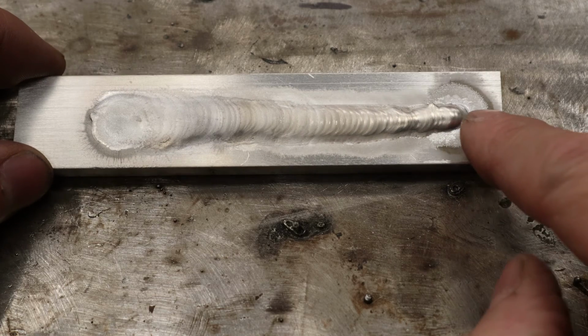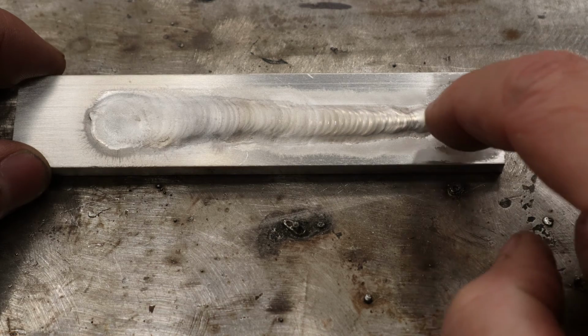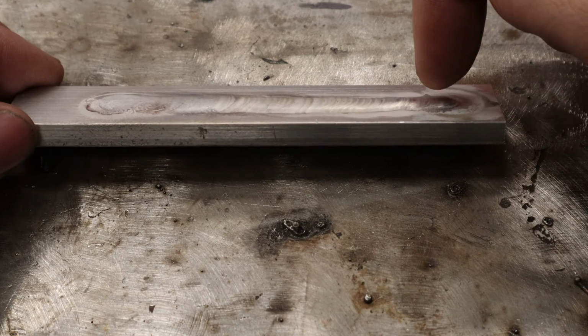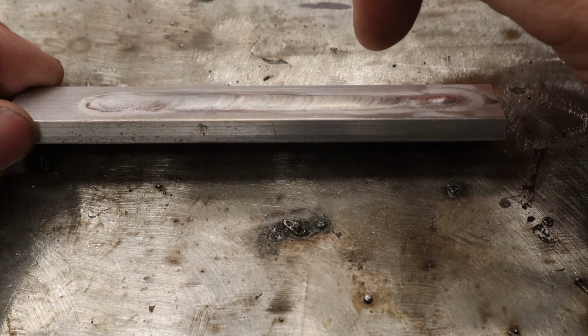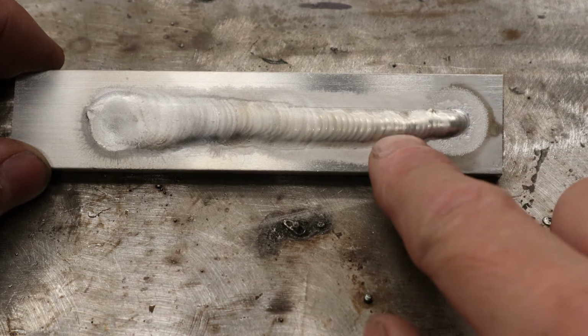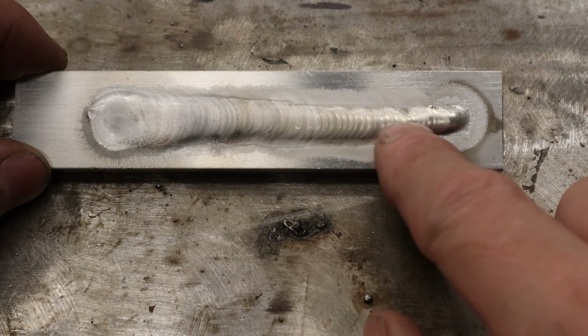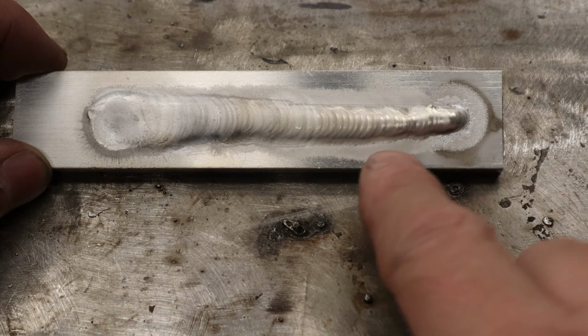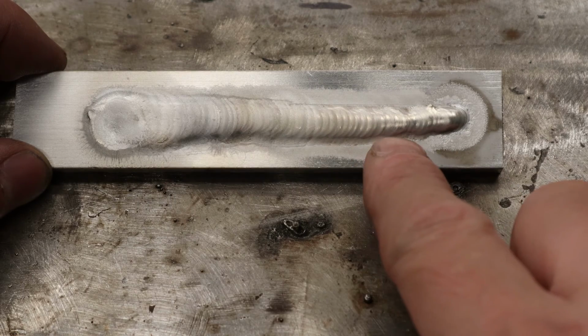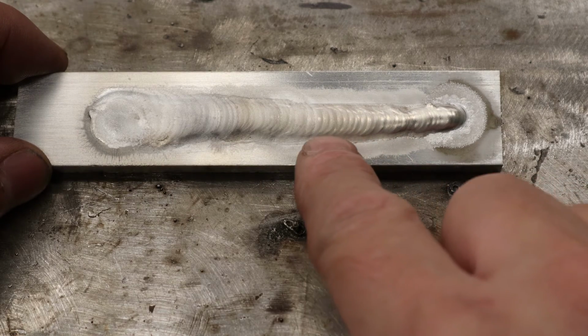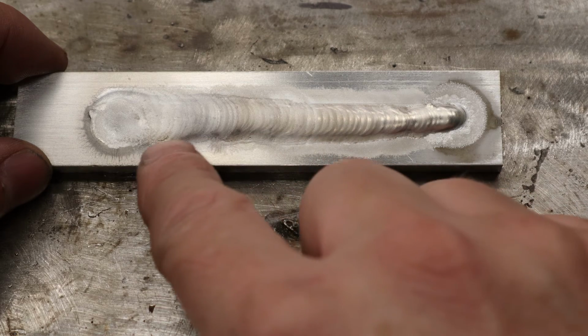With the sample here, you can see it started off okay, but as I started moving, I immediately started to slowly raise the distance that the electrode was away from the material. And somewhere around here would have been probably twice the diameter of the electrode. And as I gradually raised it, you can see that that weld pool, that puddle, the bead starts to get wider as I get going.